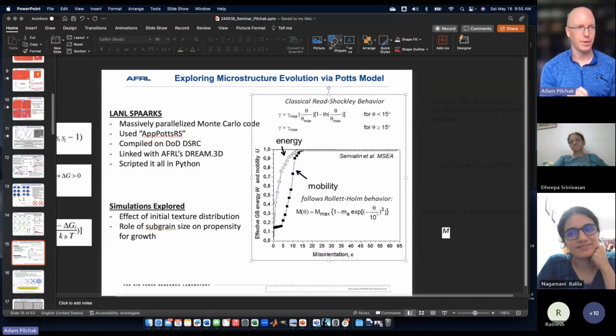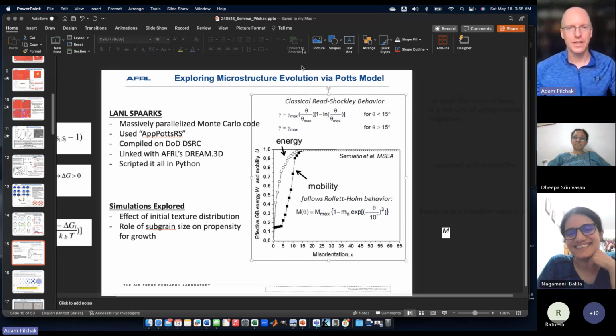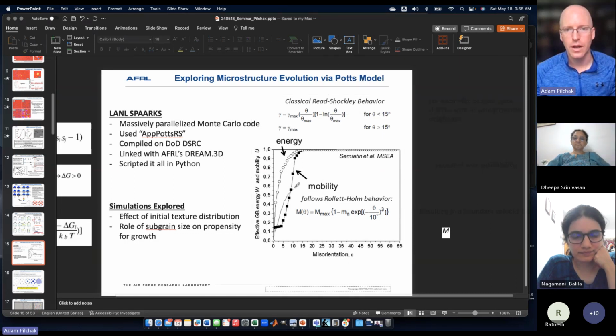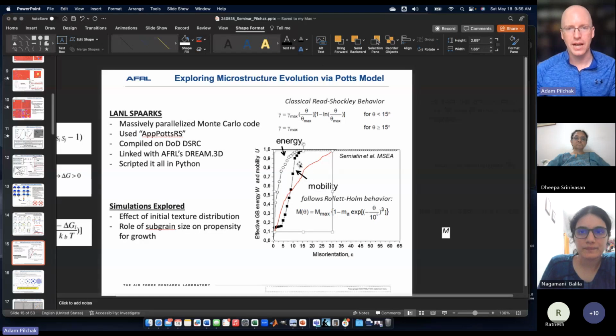And then we had also applied my reconstruction code, so we had really good measurements of the beta phase orientations. And then a postdoc that I had tried to get it across the goal line. She was very computationally savvy and ultimately determined that the grain boundaries in our sample were not perpendicular enough through the thickness to make the assumptions that go into reducing the data. So we got nothing useful out of it. But what I will say is for BCC metals, this curve is definitely shallower. Pretend that that's a smooth curve, but for BCC, the Read-Shockley equation, assuming the critical angle is like 30 degrees, is probably the best estimate that I have right now.